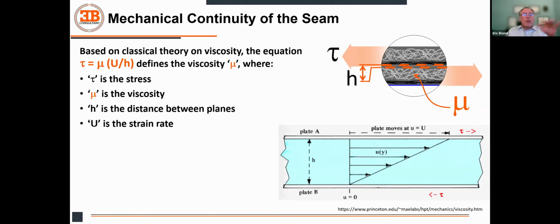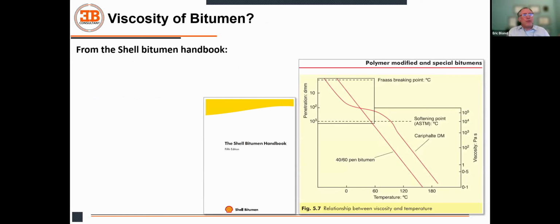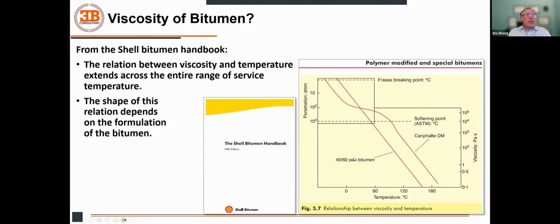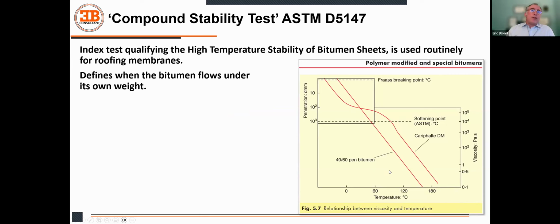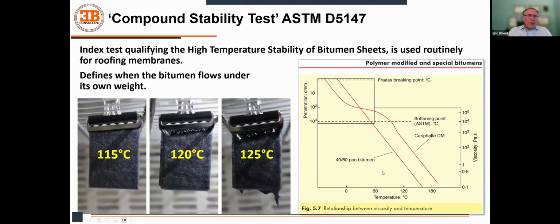We're into well-known science. So what is the viscosity of bitumen and how can it affect the performance of the seam? If we look in the Shell Bitumen Handbook, which is the Bible of bitumen, used for pavement construction, for roofs, for everything, it's really how to deal with bitumen, we can find a general trend connecting the viscosity of the product with the temperature. We see here that the relation with temperature extends across the entire range of service temperature, and that it is relatively linear. Now, what is the limit to that?